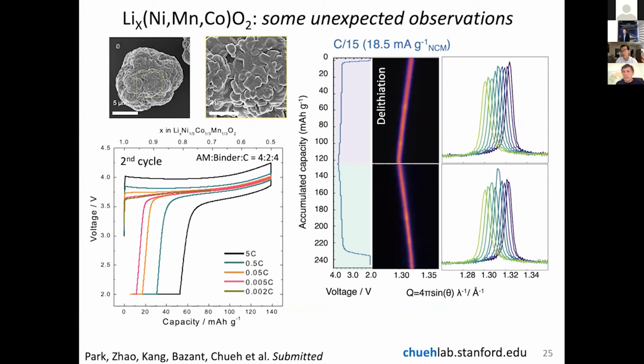If you take this material and you cycle it, you put lithium in, you take lithium out, and you use X-ray diffraction to monitor the phase behavior. Because it's a solid solution material, from Vegard's law, we know that the lattice constant should shift continuously with the amount of lithium that you take out and put in. And this is exactly what you see when we do the experiment over 15 hours. We have continuous variations of lattice constant. And moreover, it's identical between taking lithium out and putting lithium in. So this is telling a very standard solid solution picture.